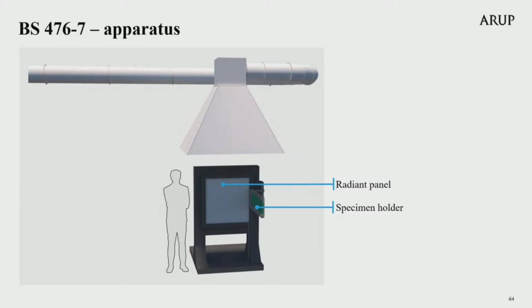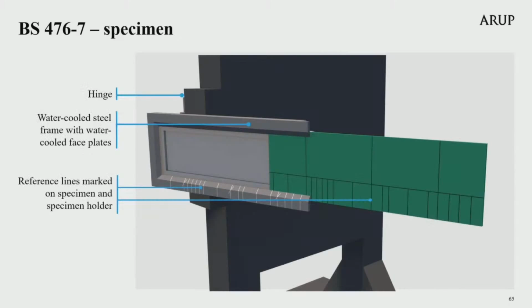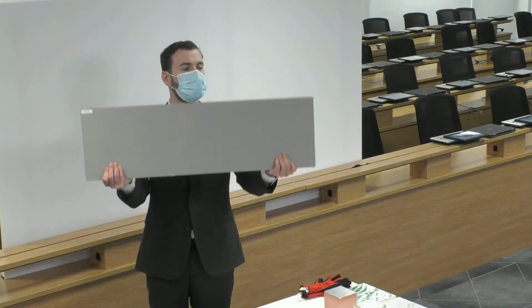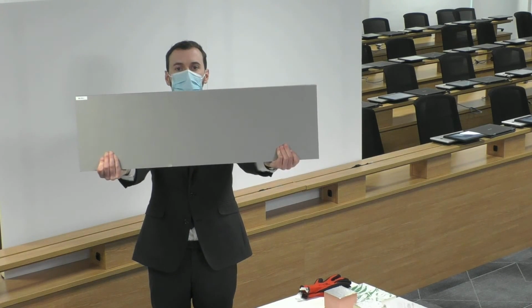The Part 7 apparatus consists of an 850mm by 850mm radiation panel mounted vertically in a surround and supported on a framework. The specimen holder protrudes perpendicular from the radiating surface. A small pilot flame tube is also provided as part of the apparatus. This is the largest specimen required for a national reaction to fire test, and each specimen is a rectangle measuring 885 millimetres long and is 270 millimetres in height. Tom is now holding up an exact replica of the Part 7 sample.